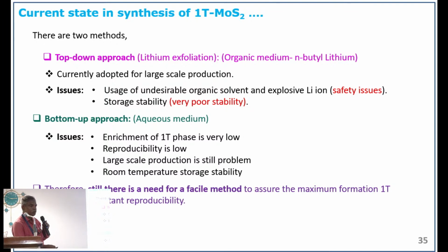So the reproducible result may not be attained the same. And the third one is that large-scale production is still a problem, because we are producing only milligram level in this aqueous medium. And room temperature storage stability is very important, because you can prepare 1T MoS2 with 30 to 40%, but if you store it at 25 degrees, the stability will be very low. Within 2 or 3 days, you will convert back into the 2H phase.